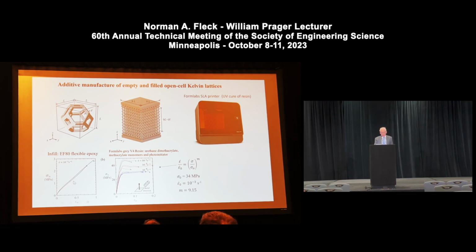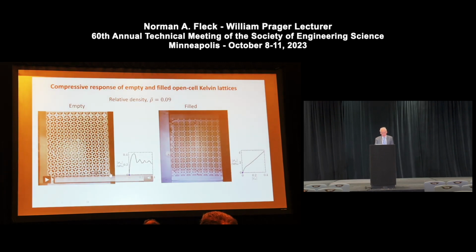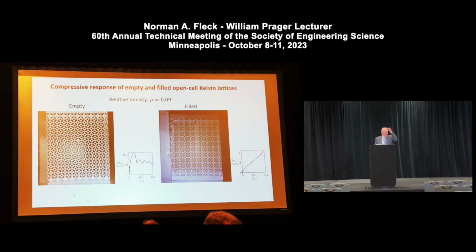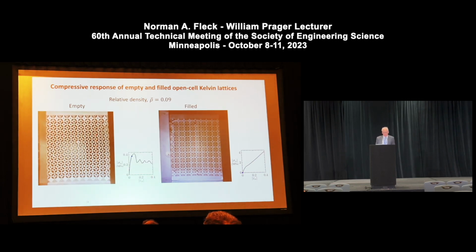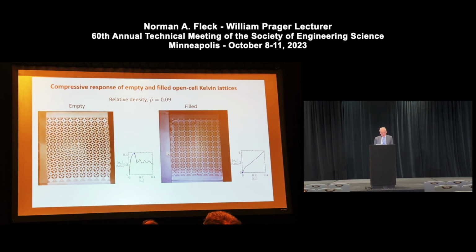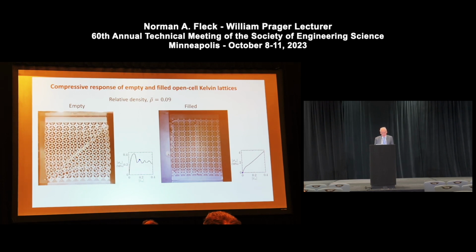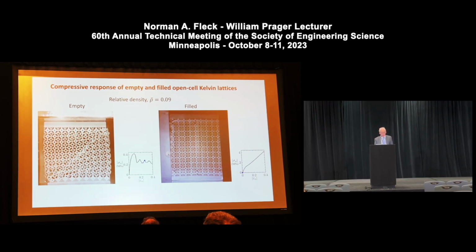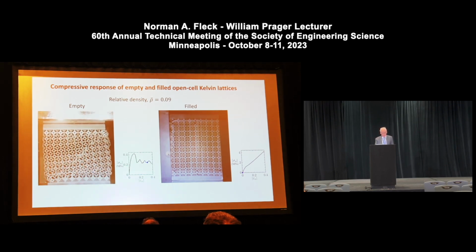And so we made a bunch of lattices, and we compressed them. We had control of the lattice in terms of its geometry, dimensions, and so on, and we could fill the lattice, as I said. So just to get a feel for how the response is, just as we saw for the case of the metal foam, one gets crush band formation. In this case, the ductility of the polymer isn't as high as that of the metal, and so fracture takes place. One can get inclined crush bands or just transverse crush bands.